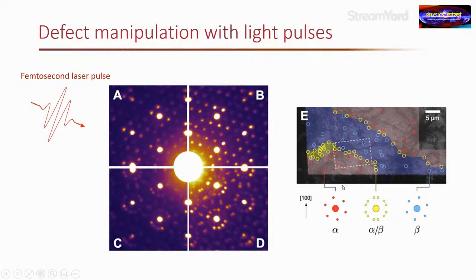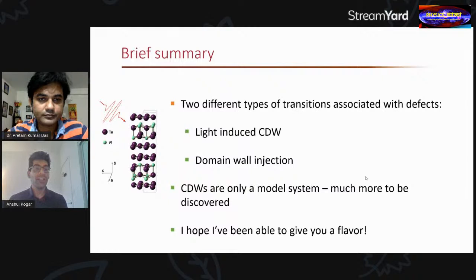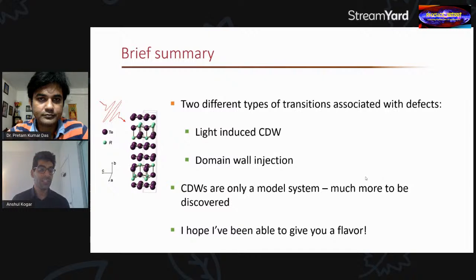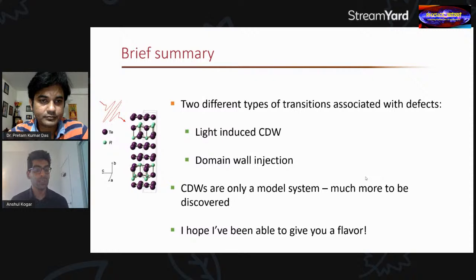To summarize: we've looked at two different charge density waves. In lanthanum tritelluride, a light-induced CDW along the a axis appears very transiently after excitation. In tantalum disulfide, shining a light pulse injects domains and domain walls that last for an indefinite amount of time — essentially forever. These are just two examples of charge density wave systems studied with these ultrafast techniques, and there's a whole range of other systems one might study out of equilibrium.